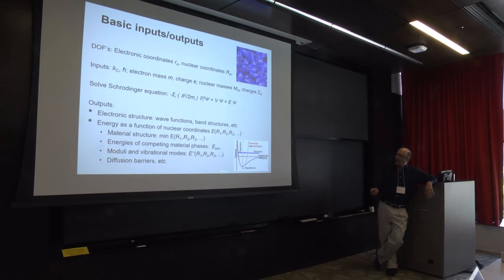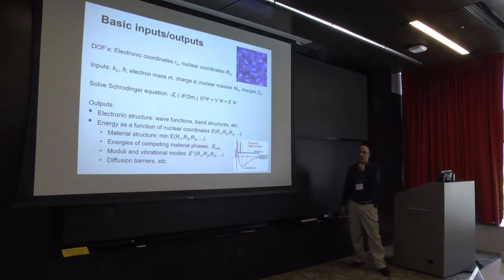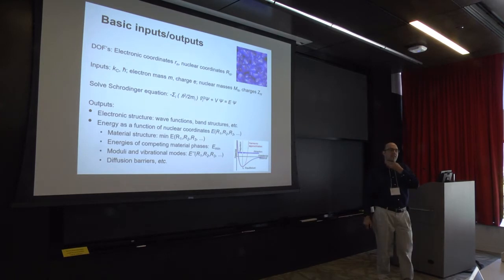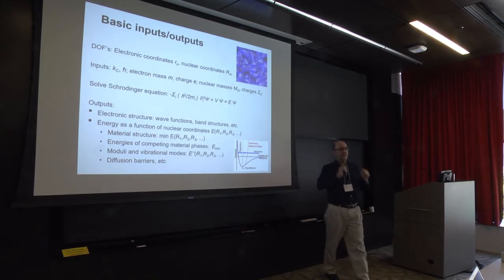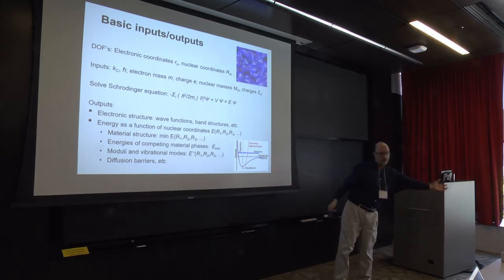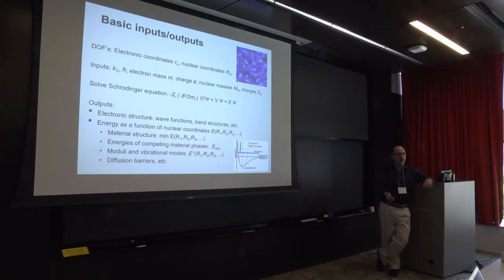One question. You said that the Schrödinger equation approximation, the way we solve it, is a few percent error. But is that depending on the size that you deal with? That's why I express it as a percentage. So the percentage is pretty much a fixed percent type error. If I wanted the energy of a crystal, it really has a certain energy per unit cell of the crystal, kilojoules per mole type of a thing. So we get that within a few percent, independent of the size. Yeah, more or less, yeah.